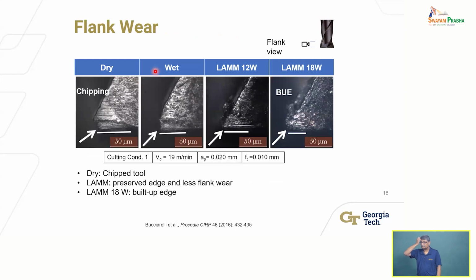Yes? Thermal expansion, how does it increase the depth? The expansion is what dimension? All dimensions, but usually in this particular case, you're only heating a very small region right in front of the tool. So that's the region that will exhibit the most expansion, because the temperature outside the region that is irradiated by the Gaussian beam is not going to be very high. You don't want it to be, obviously. So much of the thermal expansion is going to be at the point of irradiation and also closer to the tool. There is a distribution of heat, right? So you will see that thermal expansion.